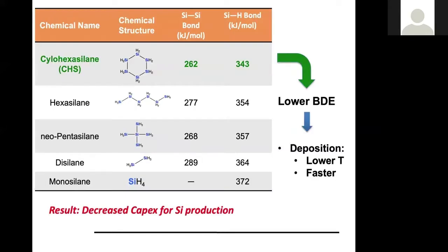So comparing CHS to a wide variety of commercially available silanes. Two things that really highlight why it has such unique properties are the comparatively lower silicon-silicon bond energies and the silicon-hydrogen bond energies. This idea of having a lower bond dissociation energy ultimately leads to faster deposition rates and deposition at lower temperatures.